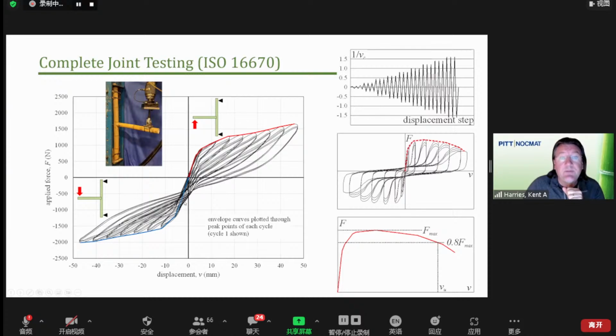And so we have these plots. And in this particular case, we tested 20 assemblies, and this just happens to be one representative one. The envelope curves are then plotted, and just for convenience, I plotted the positive envelope in red and the negative envelope in blue. And what I'm going to do for all the rest of the plots, I'm going to flip everything up to the upper right-hand quadrant. The positive and negative aspect isn't particularly important. So we're going to move everything up into the upper right-hand quadrant, the red and the blue.